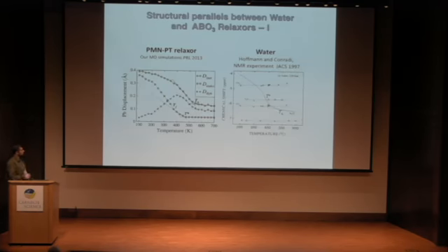But what about structure? So the first thing we can look at is a simple, very local order parameter over here that we found for the relaxer transitions, and that's the displacement magnitude of lead inside its O12 cage. And we can compare it to the data that people obtained in 1997 for the chemical shift of water. So the 1H chemical shift of water is proportional to the number of hydrogen bonds. That has been shown by MD simulations, and I think by experiment also.